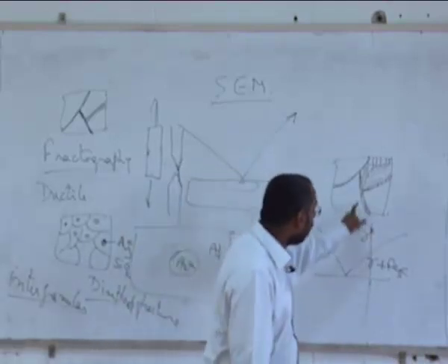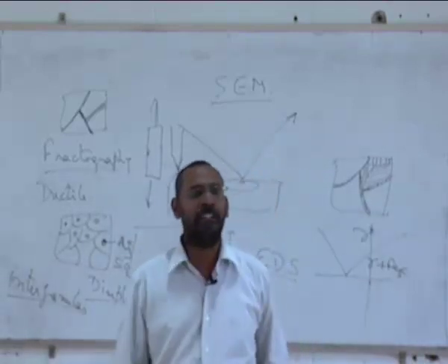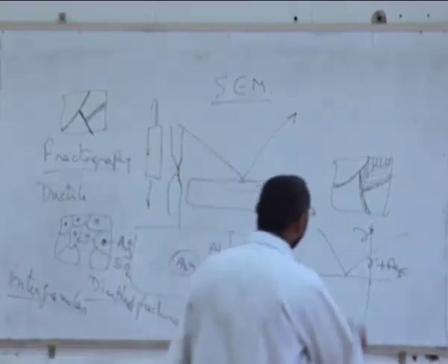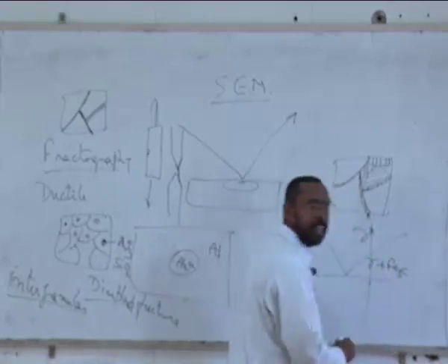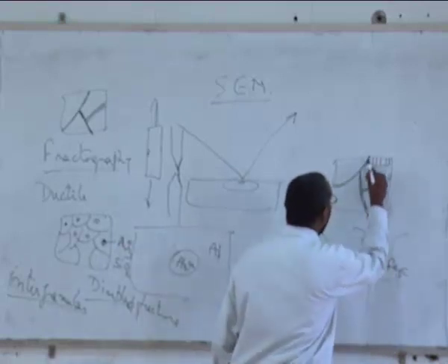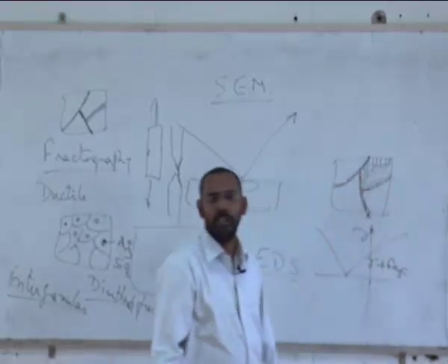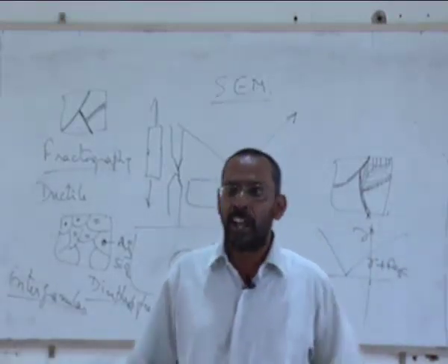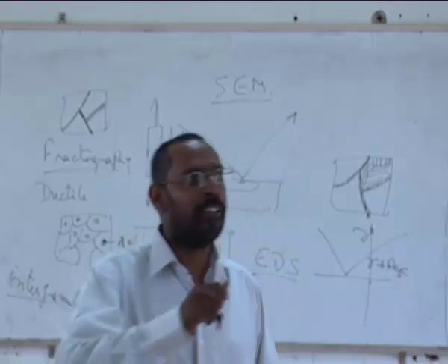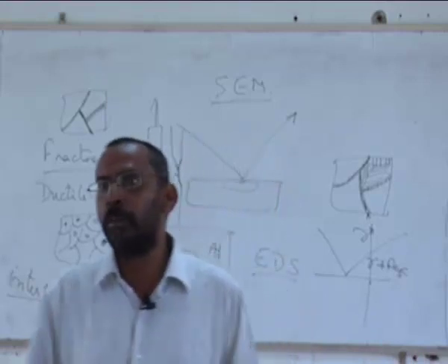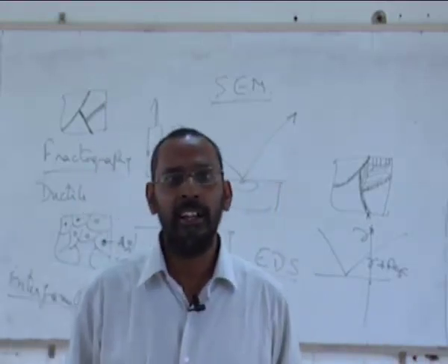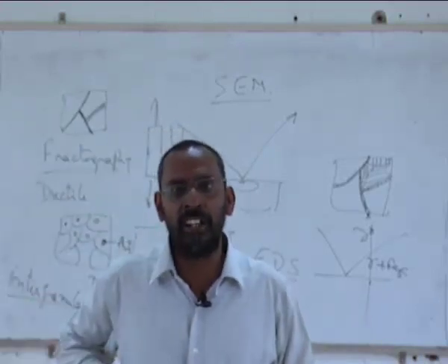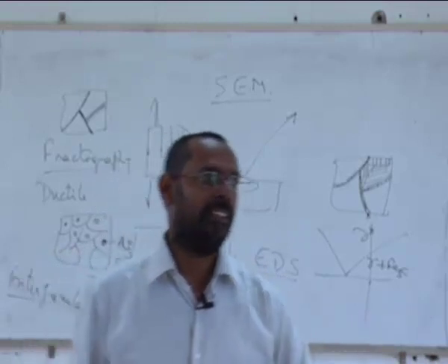Now this cementite which is there at the grain boundaries is very brittle. Right? Because it's a hard compound. So as a result, the moment a crack initiates inside the material, the crack can easily propagate along the grain boundaries. That is the advantage or disadvantage of brittle materials. If you have ever seen a person breaking glass for making frames, he will just draw a scratch on it and simply bend it, and it breaks.